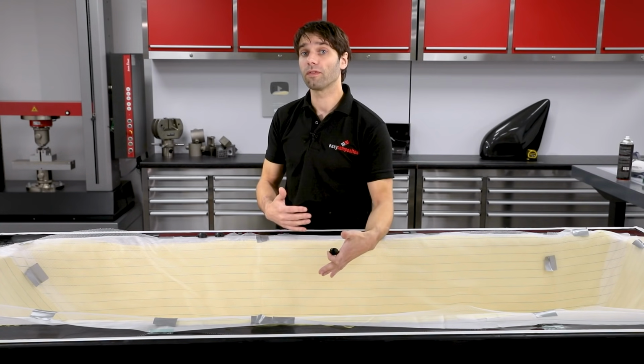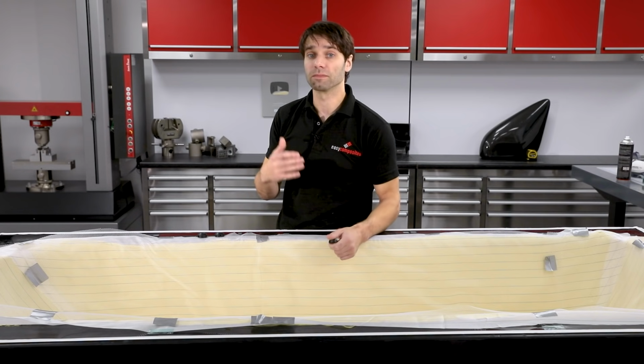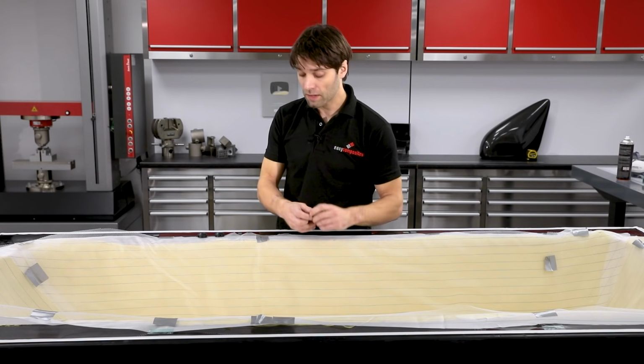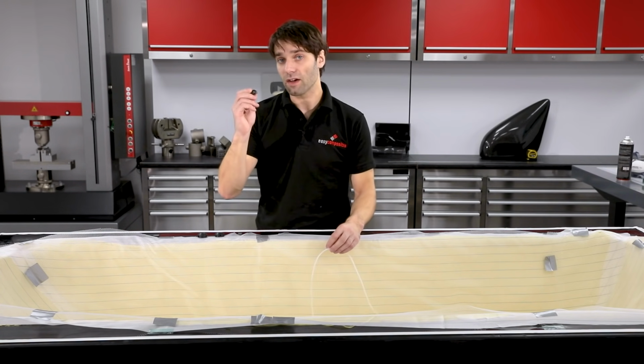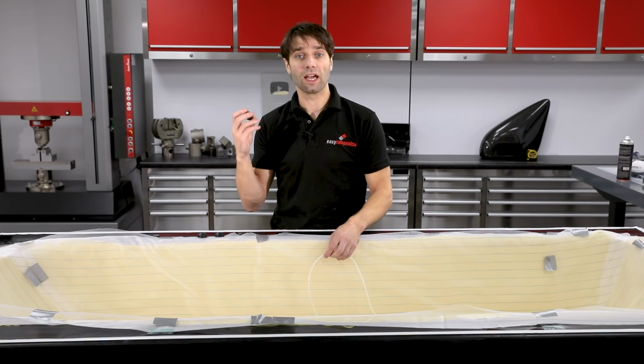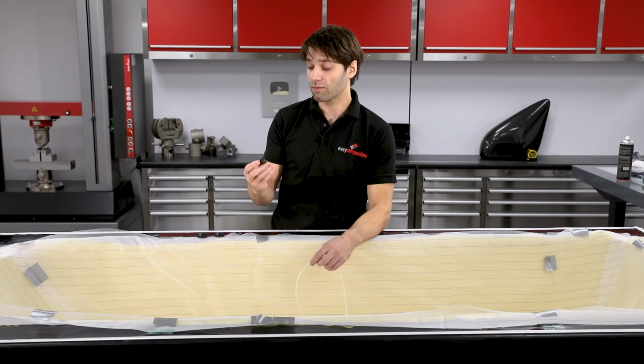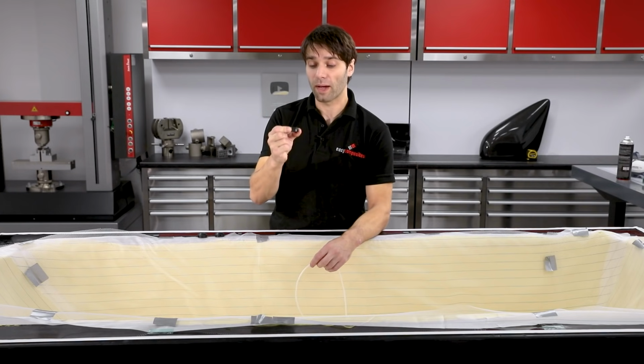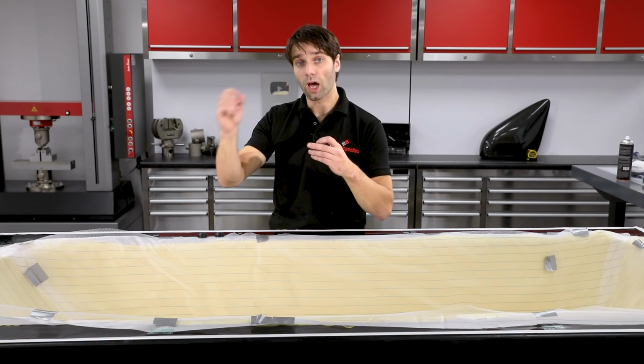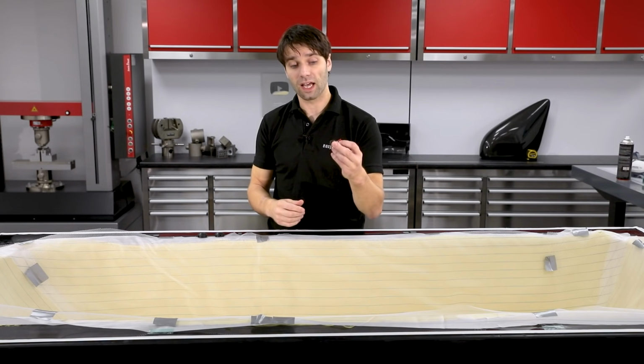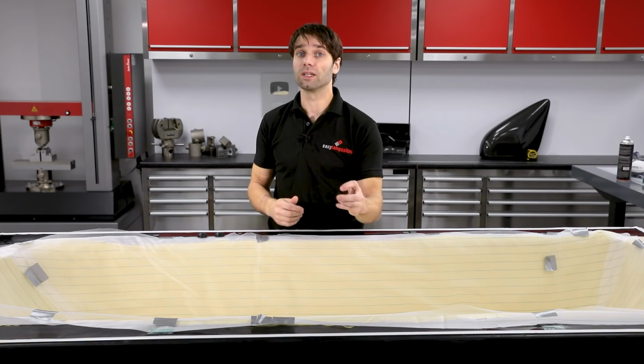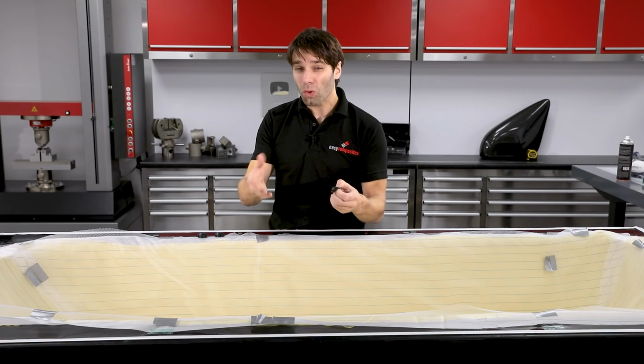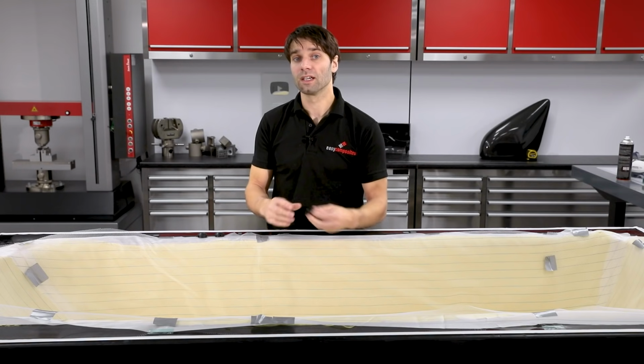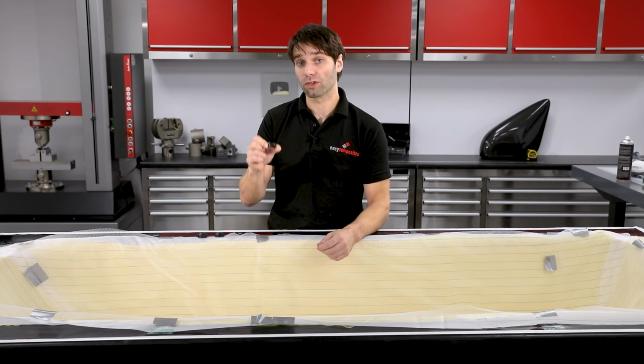If you can keep it under half a metre, your infusion times generally will be very quick. The next thing is the resin feed lines. If you're doing an infusion that's going to take 10 kilos of resin, this will be the point where you get the most restriction. The small hose that feeds in and the resin feed line. These particular connectors that we're using today, we would say normally around about 2 kilograms of resin is about an appropriate amount to run through each one.